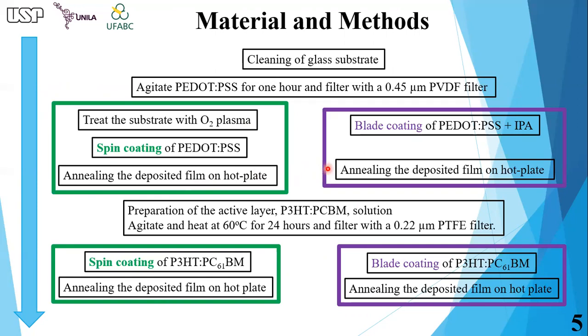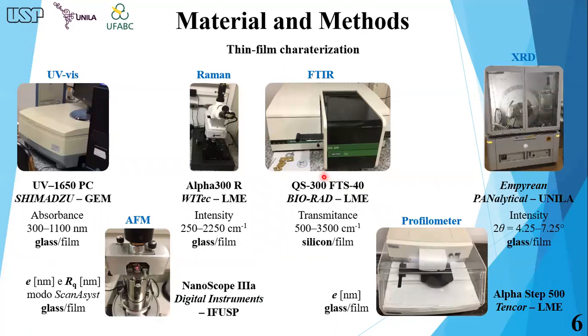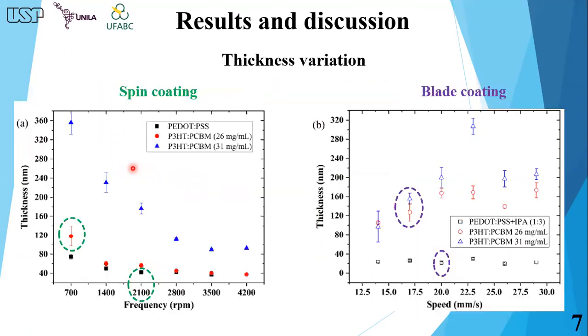The optical, morphological, and structural characterization of the thin films were made on the equipment shown. Film thickness decreased with spinning frequency. The opposite occurred with the increase in the speed of movement of the knife for films obtained by blade coating. The circles with dashed line show the appropriate thickness for fabrication as a function of the deposition rate according to the process.